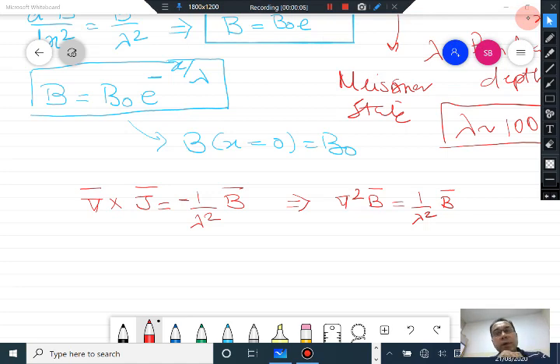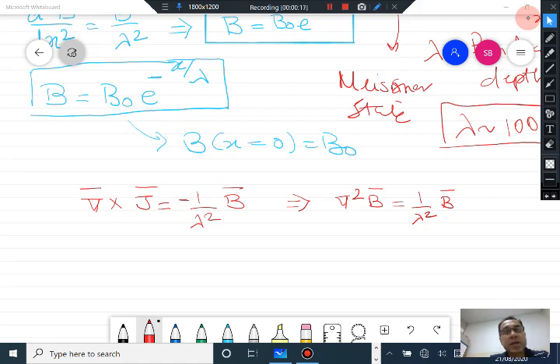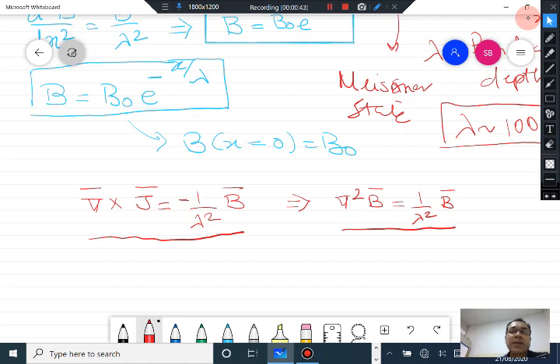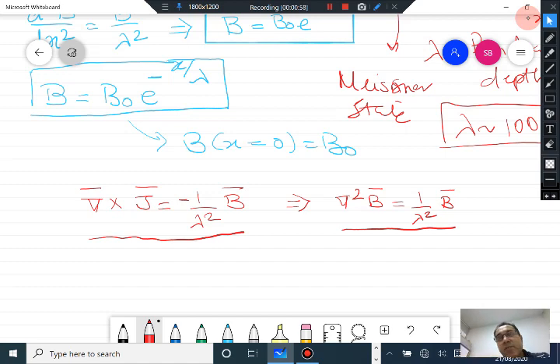In the earlier lecture we saw that the Meissner effect, which is the screening of DC or AC magnetic fields from within the interior of the superconductor, is described by London's equation: curl of J, where J is the current density. This also describes DC fields, so DC currents as well as DC magnetic fields are related by this equation. It shows that there is screening of DC magnetic fields from the interior of the sample — the magnetic field just penetrates up to lambda from the edges of the sample, where lambda is the superconducting penetration depth.